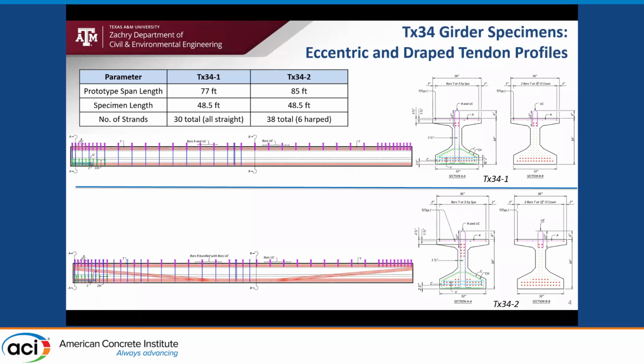One thing we were interested in identifying was the shear performance of UHPC because of the steel fibers. The steel fibers drive the cost of the mix by about 50%, and therefore we were interested in identifying the potential of reducing the transverse web reinforcement in these girders due to the higher shear performance of UHPC. What we did was have one half of the girders with minimum transverse reinforcement by design, and the other half was without any transverse reinforcement.